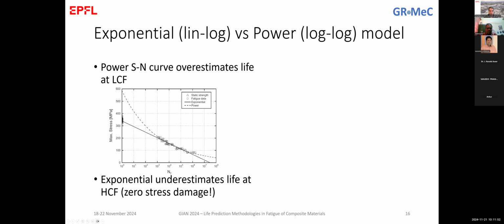So this is what is visualized here. The power curve, although can fit well the behavior of the material between, in this case, 10 to the power of 3 to 1 million cycles, then since it is a power curve, it overestimates the behavior at very low cycles or the static strength behavior that we see in this diagram.